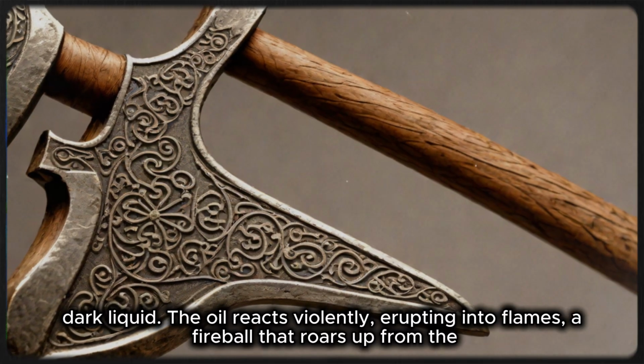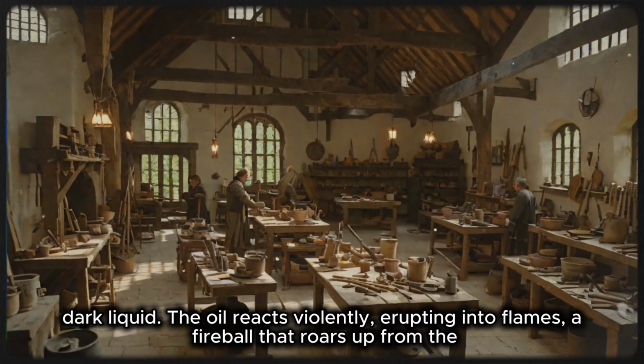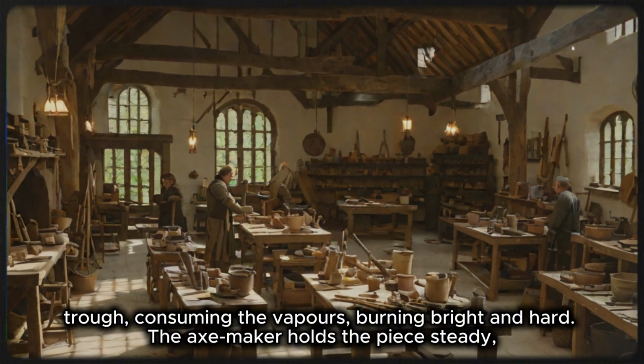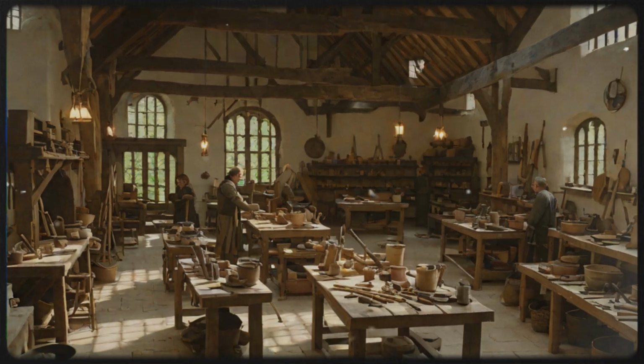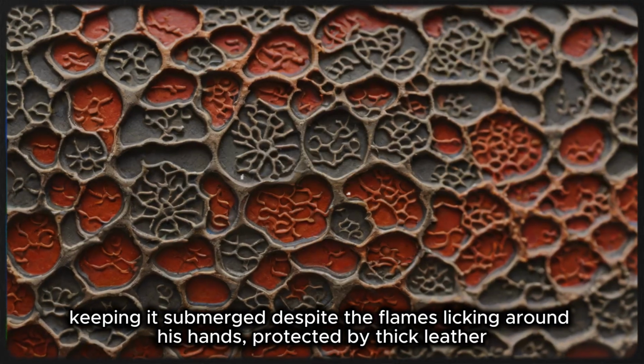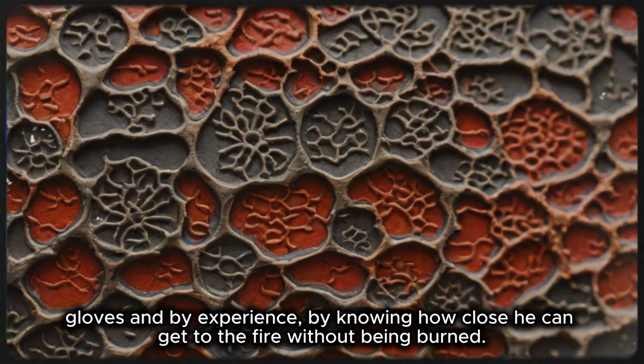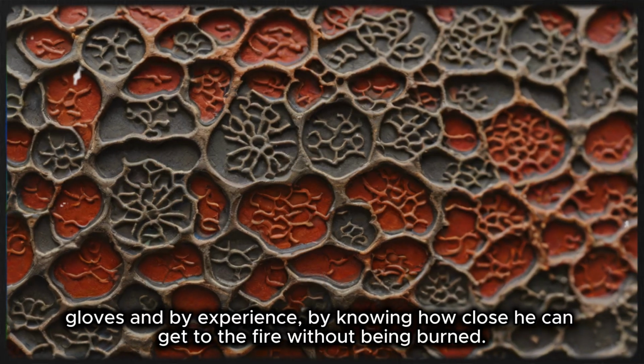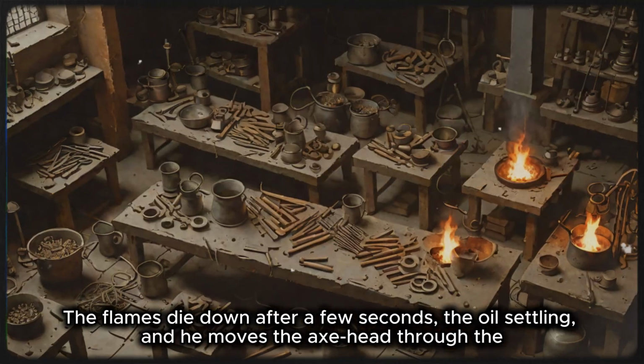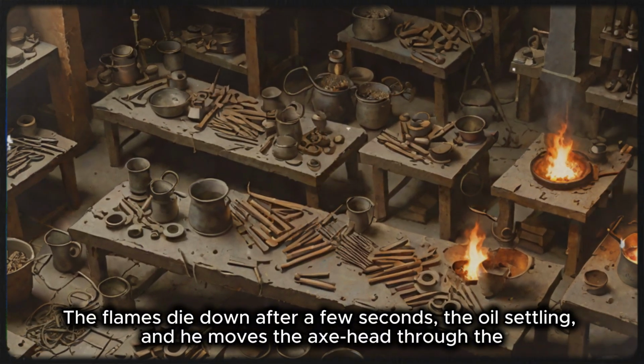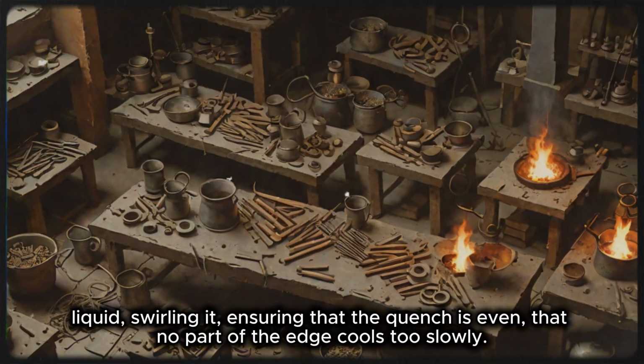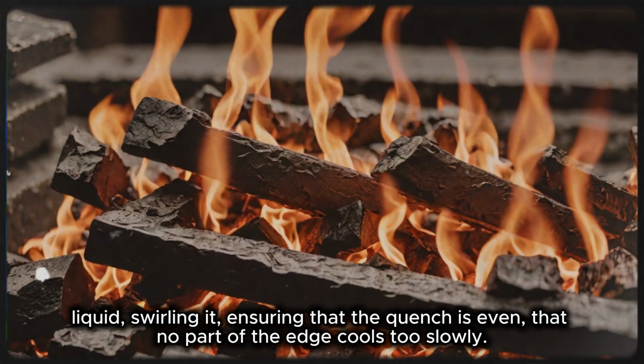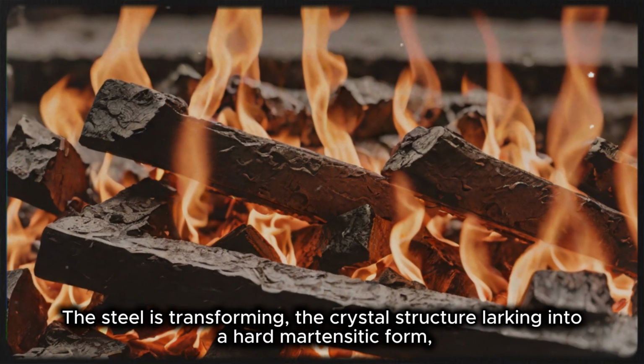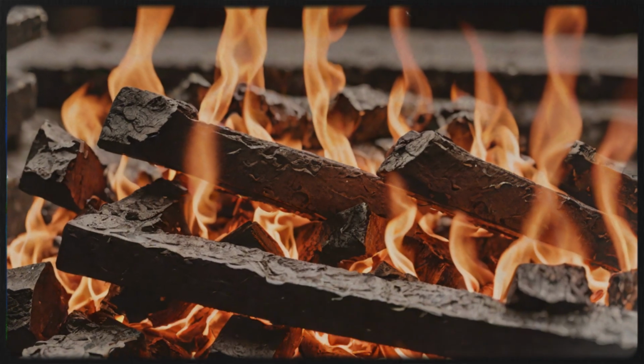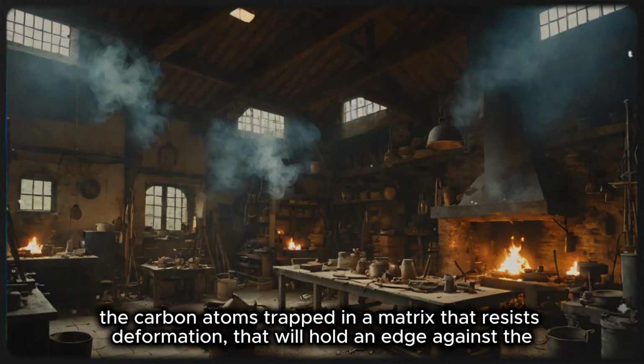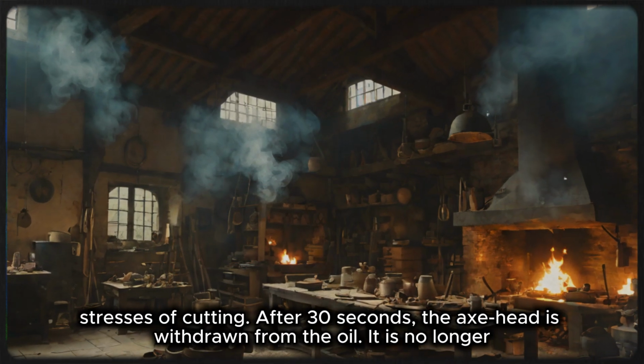The oil reacts violently, erupting into flames, a fireball that roars up from the trough, consuming the vapors, burning bright and hot. The axe maker holds the piece steady, keeping it submerged despite the flames licking around his hands, protected by thick leather gloves and by experience, by knowing how close he can get to the fire without being burned. The flames die down after a few seconds, the oil settling, and he moves the axe head through the liquid, swirling it, ensuring that the quench is even, that no part of the edge cools too slowly. The steel is transforming, the crystal structure locking into a hard, martensitic form, the carbon atoms trapped in a matrix that resists deformation, that will hold an edge against the stresses of cutting.